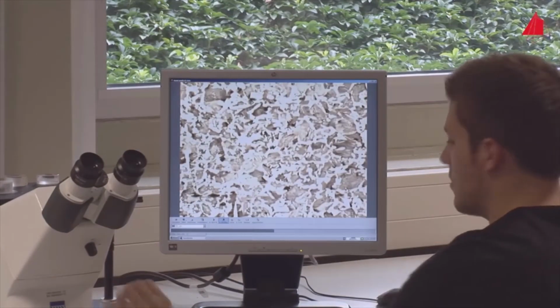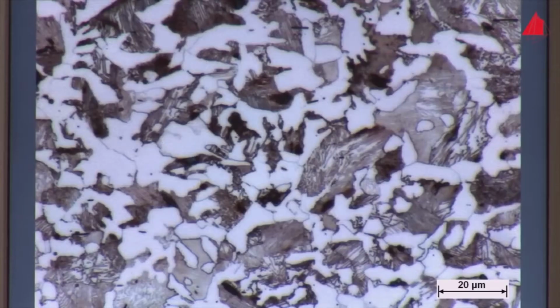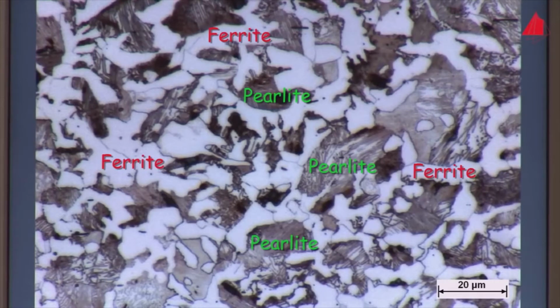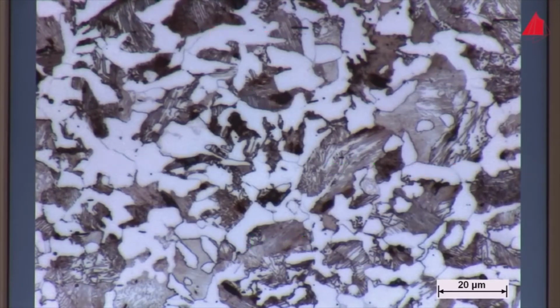At medium magnification, light and dark areas become visible. At comparatively high magnification in some of the dark areas, fine stripes may be recognized. The microstructure in the darker striped regions is termed pearlite. Pearlite consists of thin alternating crystals of ferrite and cementite. The white regions are ferrite crystals. They consist of almost pure iron. Great! The etching has been successful.